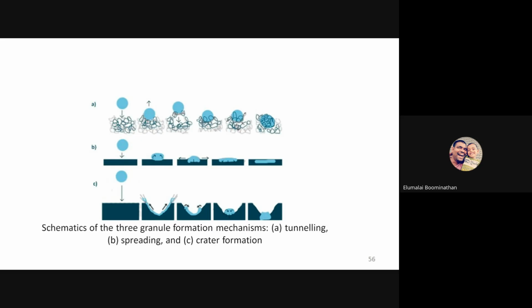These are the three possible mechanisms when the binder interacts with the powder. One is tunneling. Tunneling means the binder rolls over the surface and forms bigger chunks of powder balls. Whereas in spreading, the powder is not usually disturbed. The binder gets attached to the surface and spreads to the required area. And sometimes crater formation also takes place when the binder hits the powder surface and the powder surface gets a crater. So crater formation and tunneling need to be avoided.